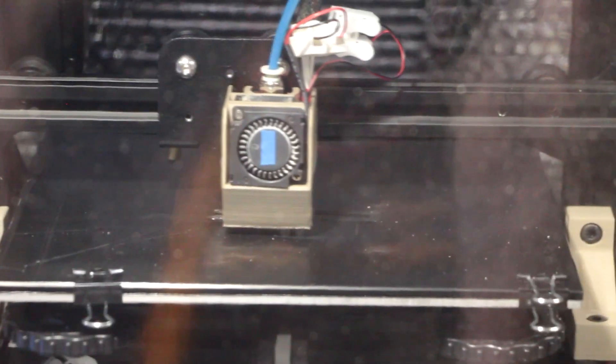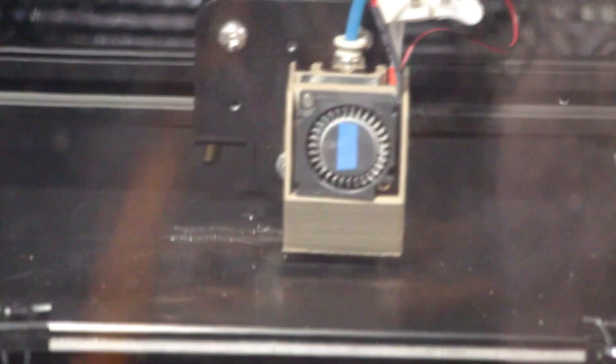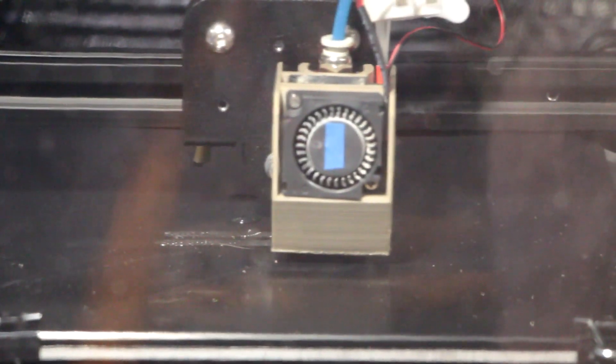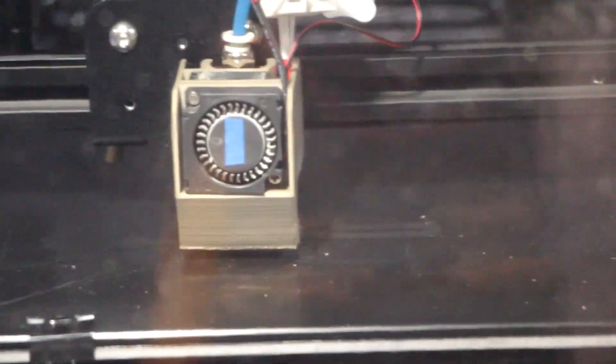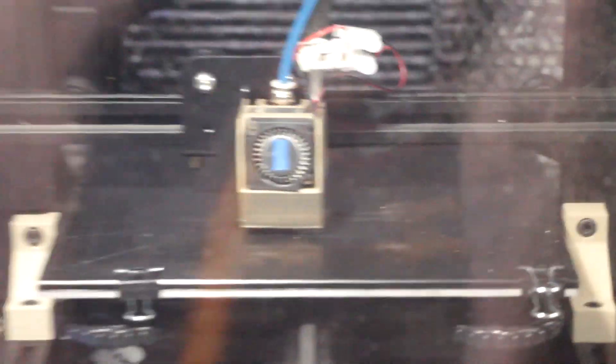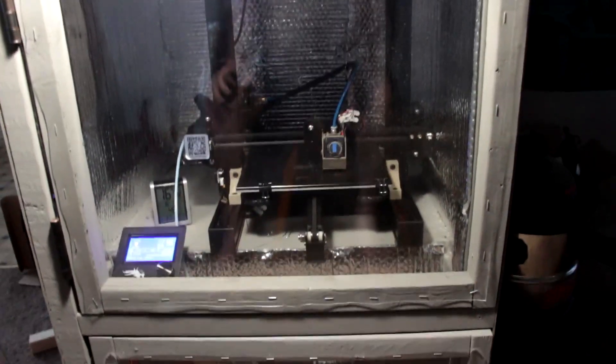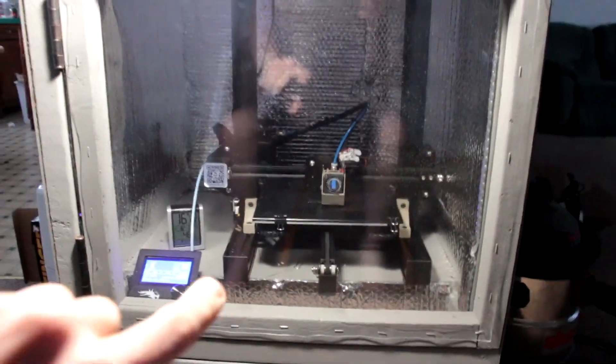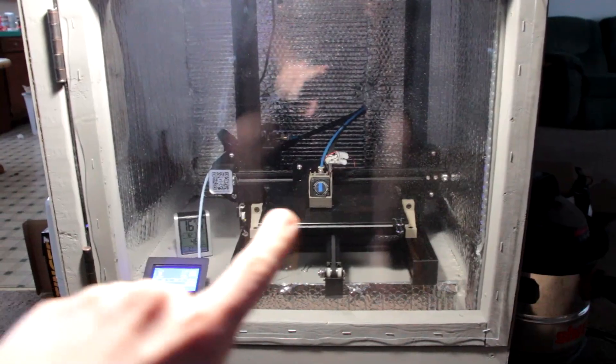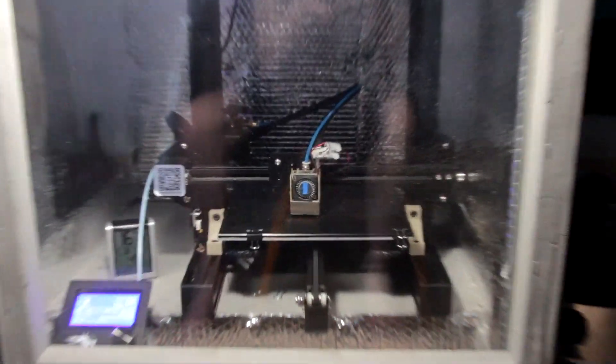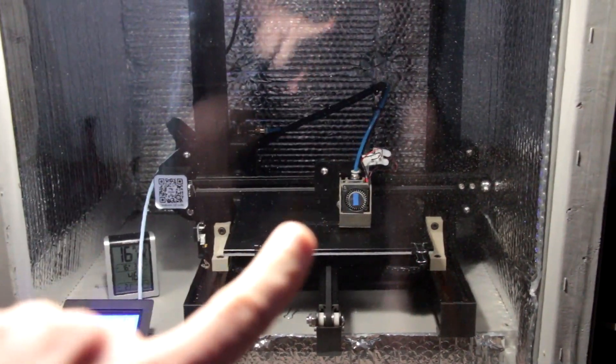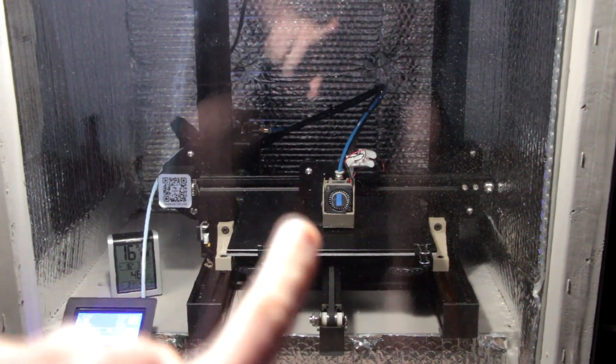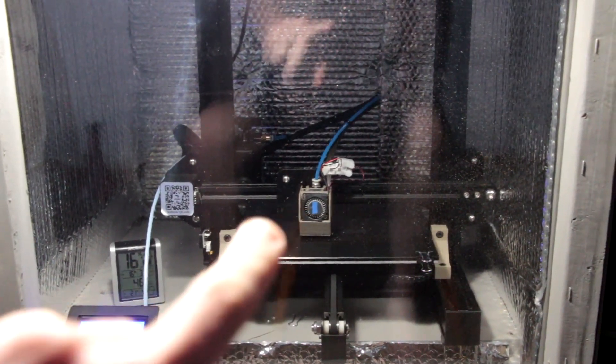The filament I'm currently running on this printer is polycarbonate, PC Max. In the past I really have not been able to successfully print that, but I've been able to do that quite well ever since I got the enclosure. The maximum temperature with the new lining tube here is up to 290 degrees Celsius. I wouldn't really run it more than that; the thermistor is not really rated so it's not that accurate at that temperature.